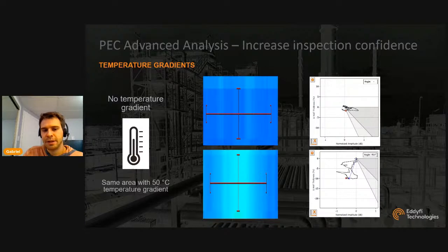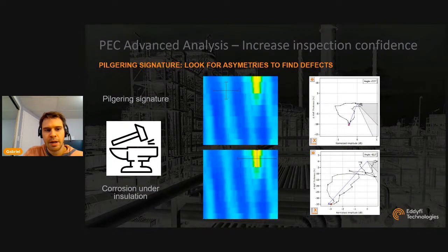We heated the center of this plate with a heating element, and we're able to generate a temperature gradient of about 50 Celsius between the ends and the center, close to 100 Fahrenheit. And we introduced a change in wall thickness measurements in the PEC signals of about 10%. And this does look like a real indication. So the tool is not able to identify or differentiate temperature gradients from actual indications. So that's one of the limitations of the tool.